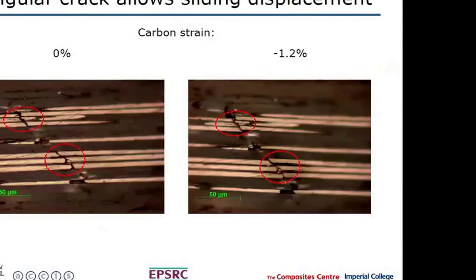So in that case, we're not seeing any failure in the intervening ply. There's sufficient margin between the carbon and the glass, but the glass does not fail. Now, again, if you use materials which were closer in terms of strain, you might be able to tailor that. And one of the things we've looked at in another part of the program is the whole idea about actually weakening the fibers locally, so that you might actually in situ generate a discontinuous composite. So it starts out with a continuous composite, you've got the modulus of a continuous composite. At a certain point, you periodically weaken the composite using lasers, then it breaks, and then you might move towards a discontinuous composite towards the failure.